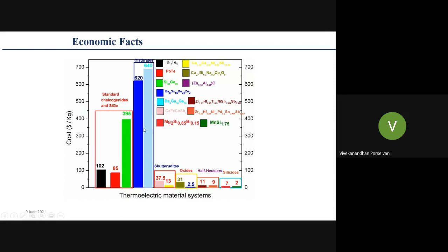Okay, talking about the silicon germanium, which is being used in real-time application, in a space application as a radioisotope thermoelectric generator, because it showcases a superior ZT of more than 1, and also this is a potential material that can work at more than 1000 degrees Celsius. That is why silicon germanium alloy is being used in space applications.